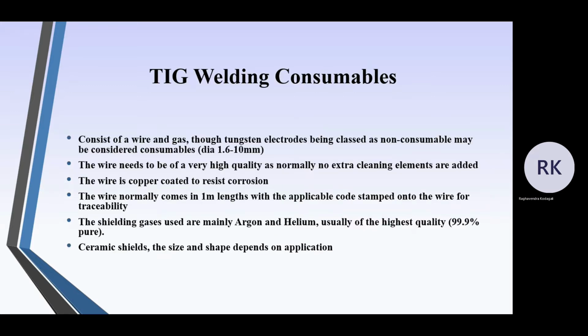TIG welding consumables consist of wire and gas. The tungsten electrode, being classed as non-consumable, may be considered a consumable. It is available in diameters of 1.6 to 10 mm. The wire needs to be of very high quality and, as normal, no extra cleaning elements are added. The wire is copper coated to resist corrosion. Wire normally comes in 1 meter lengths, with the applicable code stamped on the wire for traceability. So you can see at the end it is marked.